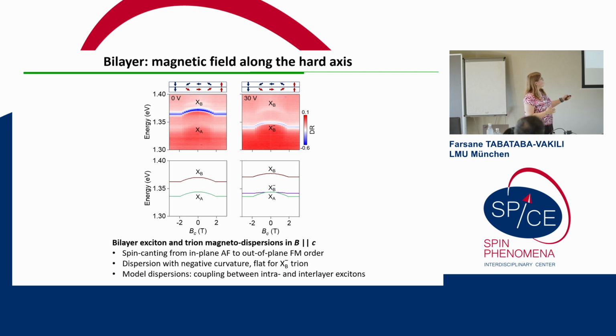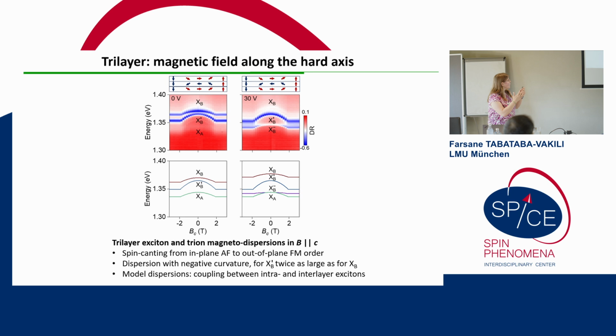And we're able to model this. This was my colleague Anva sitting in the back who did the modeling. In our model, we take intra- and interlayer exciton coupling into account, via hole tunneling, which gets turned on with the magnetic field. More about the model in a bit. Now let's have a look at the trilayer. Here, this other neutral exciton XB prime shows a factor 2 in curvature, and we're also able to capture this in our model.